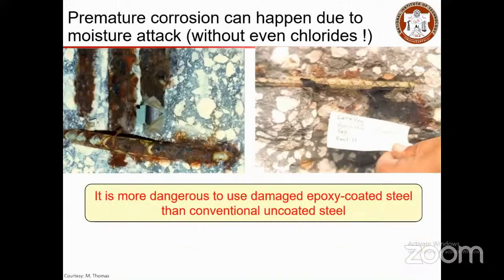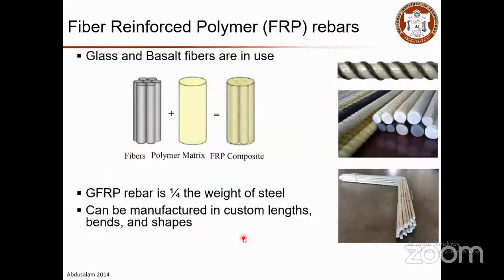Here you can see some premature corrosion that happened due to such poor practices with epoxy coated bars. The damage is more with damaged epoxy coated steel bars than with conventional uncoated steel bars. In addition to that, nowadays we are working a lot with GFRP bars. GFRP bar technology is part of regular construction practice in many developed countries, but in our country we are yet to adopt GFRP or FRP bar usage in our construction practices. We have a building code in process that will be released soon, which gives the specifications and test methods for GFRP bars from BIS.